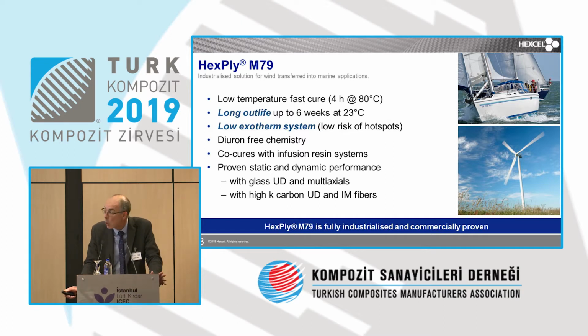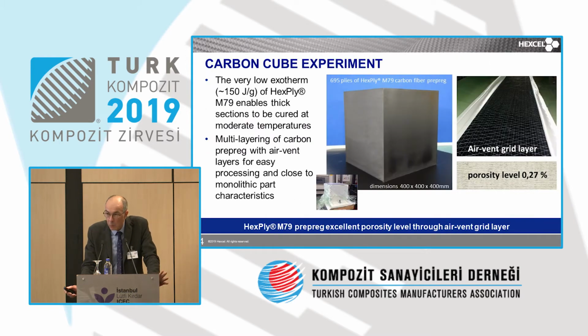The fact that it is a very low exotherm material enables thick section to be cured at moderate temperature. As you can see here, it's nothing realistic, but we did an experiment with nearly 700 plies of this material that were made to make a cube, which is quite heavy. What is also important in that technology is the fact that you can use what we call an air vent grid layer, and this will really help easy processing and the fact of having all the air going out, getting very low porosity level, and despite the thickness, really no need for systematic compacting.